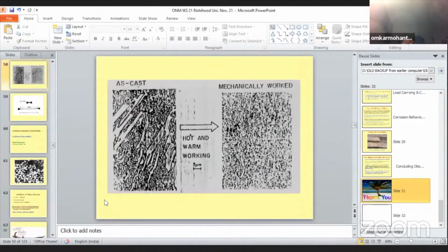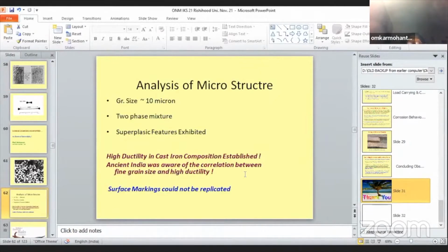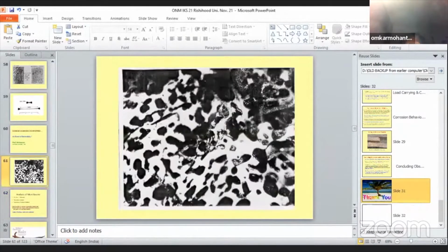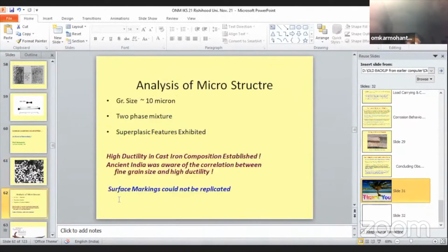The most important thing is that at the National Metallurgical Laboratory, where I spent 11 years as director, which is a part of the Government of India's CSIR, we produced it by a special process. This is how the as-cast material is, elongated and very brittle, but by hot and warm working, we produced mechanically worked material with extremely fine precipitates. Analysis of the grain structure shows it is 10 microns or less. It's a two-phase mixture, and in the electron microscope we saw a white phase and a dark phase. The dark phase is the carbide, which is very fine, only a few nanometers. The two phases, one hard and one soft, give you superplasticity or very good ductility.